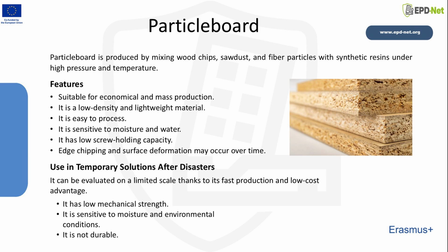However, because the particles are randomly distributed and not directionally aligned, the internal structural continuity is limited. Unlike plywood or OSB, particle board does not have directional reinforcement. Therefore, its mechanical behavior is isotropic but relatively weak. Mechanical properties. Particle board has low bending strength, limited tensile capacity, weak screw holding performance, low resistance to cyclic loading. These characteristics make it unsuitable for structural use. Under load, it tends to deform permanently, experience edge breakdown, lose structural integrity when exposed to moisture. In humid conditions, the board absorbs water, causing swelling and loss of mechanical properties. Once swollen, it does not return to its original strength.